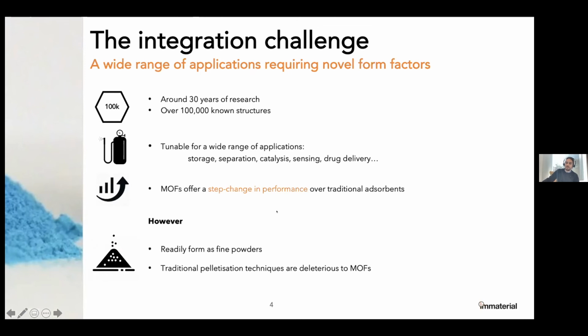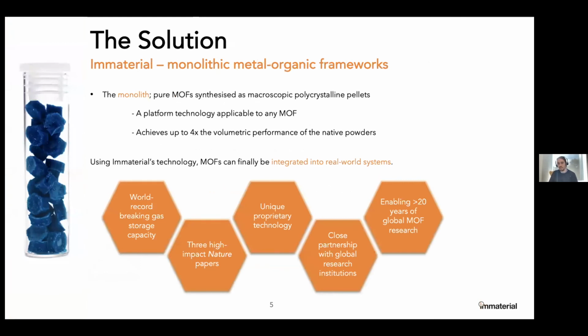So that's where Immaterial's key piece of technology comes in, and that's this monolithic structure, which I mentioned earlier. You can see some examples on the left-hand side of what our monoliths look like. A monolithic metal organic framework is really a macroscopic polycrystalline pellet, so it's all about the control of crystallization when we're producing these metal organic frameworks. We've done this now with tens of different structures, so as far as we can tell, it's applicable to any metal organic framework. We believe it works with any of the 100,000 known structures, but we obviously haven't got round to trying all of them yet.